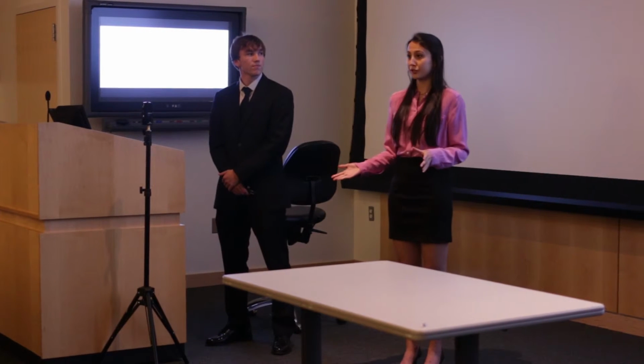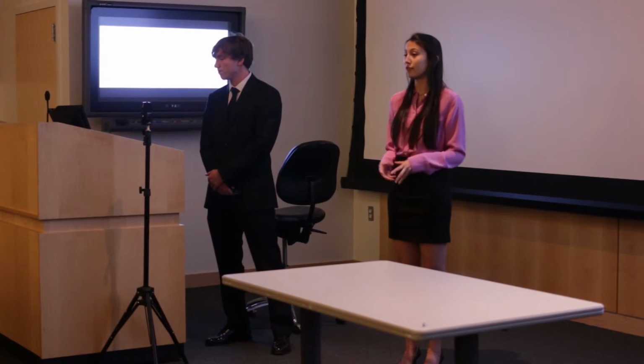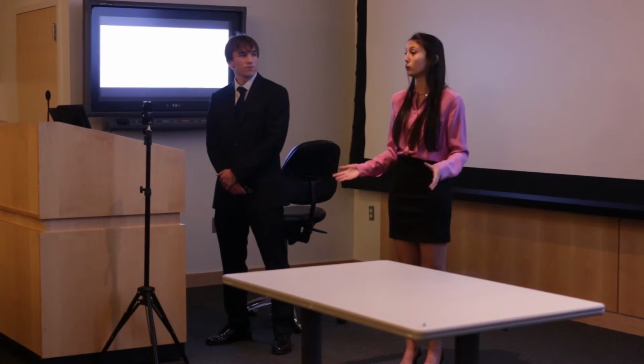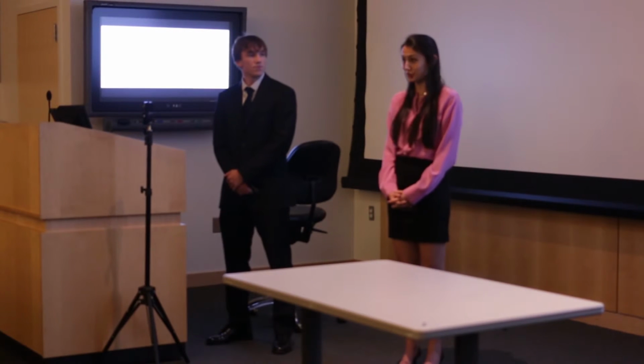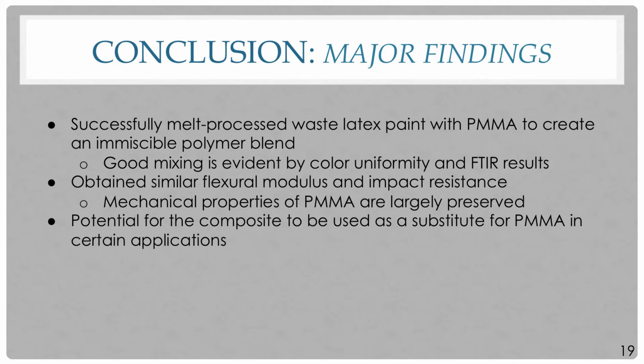So we set out with our research to create and determine the properties of a 20/80 paint PMMA polymer blend, which we were successfully able to do. For one, we melt processed the waste latex paint with pure PMMA to create our immiscible blend, which was evidenced by the uniform gray color we achieved throughout all of our specimens, as well as the consistent results we got from FTIR testing. From our research, we also obtained very similar values for flexural modulus and impact resistance, which shows